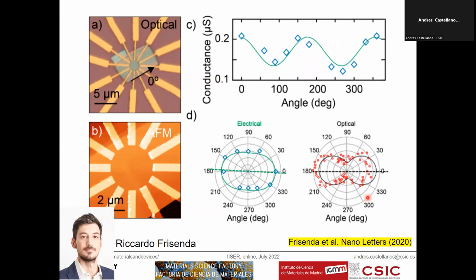Surprisingly enough, Franckeite is an anisotropic material. Basically you have a square lattice and a triangular lattice, making this superlattice, one on top of each other. If you just take your Illustrator or Inkscape and plot this square lattice and a triangular lattice, and put them on top of each other, you will see that you cannot explain an in-plane anisotropy, because both lattices are isotropic.